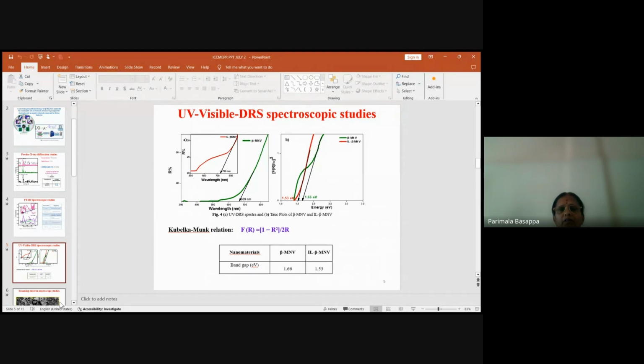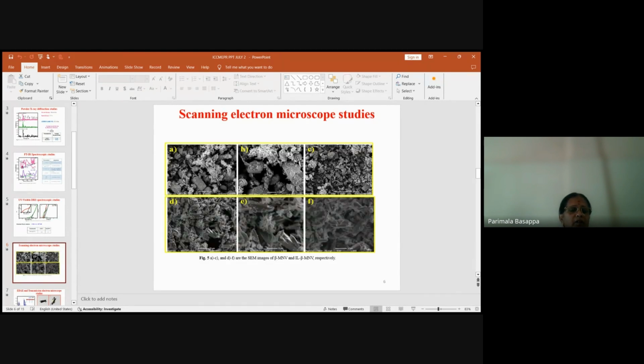And we have carried out UV visible DR spectroscopic studies to calculate the band gap. You can see this is beta manganese vanadate, and the red color is ionic liquid manganese vanadate. So when the bare component is treated with ionic liquid, we can see the band gap is decreased. The decrease in band gap is essential for these battery studies. We have carried out lithium-ion battery studies and also the supercapacitor studies.